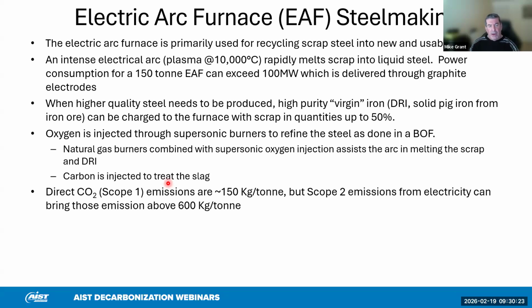But typically, compared to the basic oxygen furnace, the Scope 1 emissions are quite low, 150 kilograms per ton. Scope 2, though, if the electricity for melting the steel is produced by burning fossil fuels, we can suddenly see a rapid rise in the overall emissions to above 600 kilograms per ton.